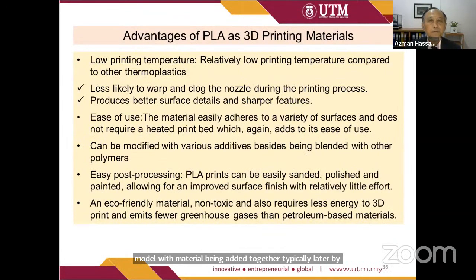What are the advantages of PLA as a 3D printing material? Firstly, it has a relatively low printing temperature compared to other thermoplastics, because of its low Tg and also low crystallinity. Therefore, it is less likely to warp and clog the nozzle during the printing process and produces better surface details and sharper features. It is easy to use, it can be modified with various additives, as I have mentioned, it has easy post-processing, and it is an eco-friendly material.